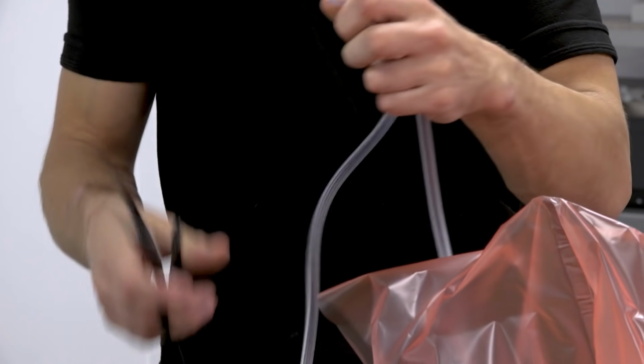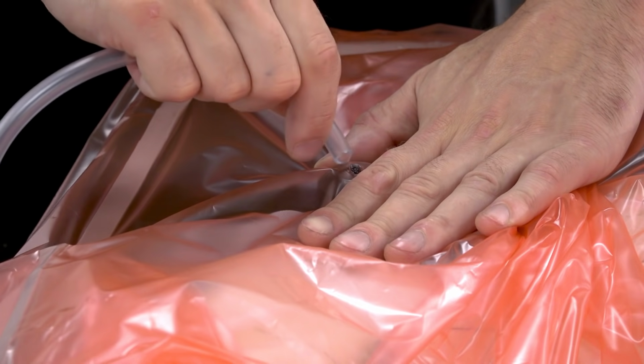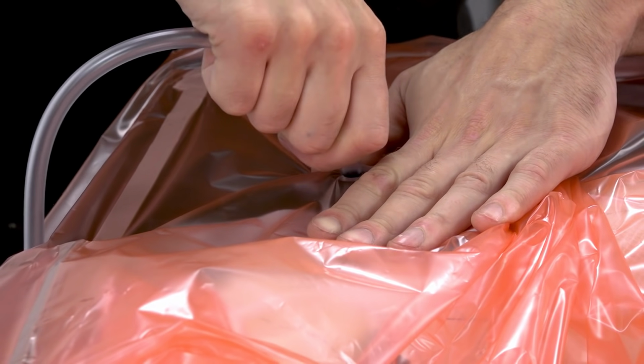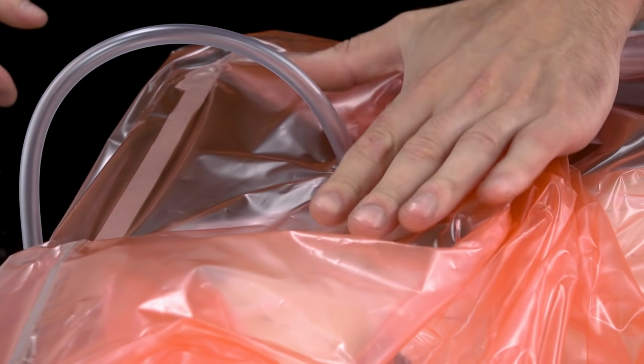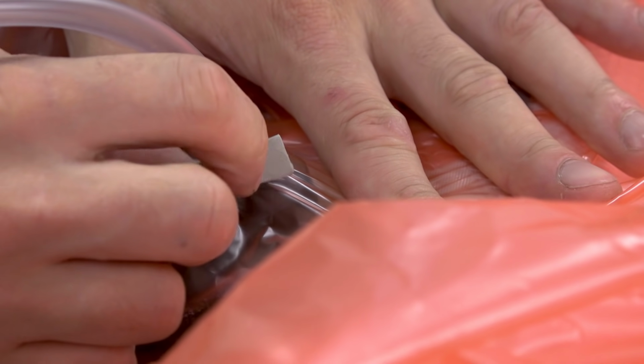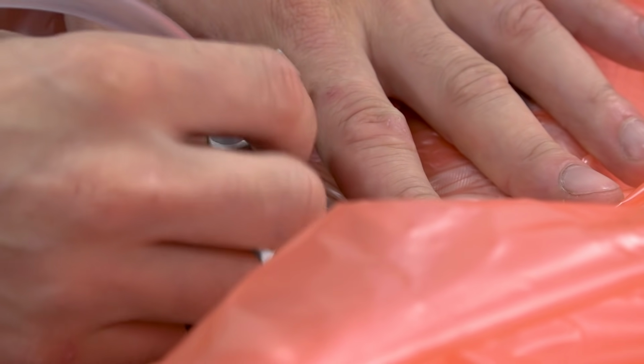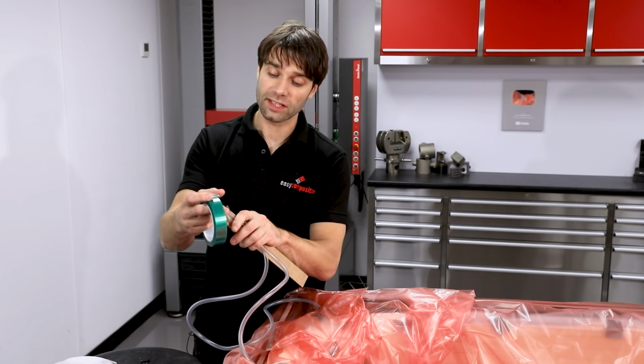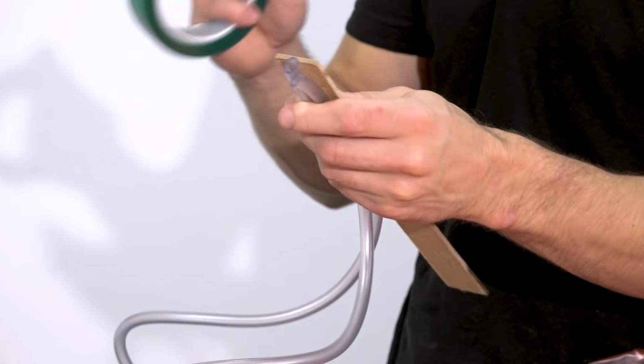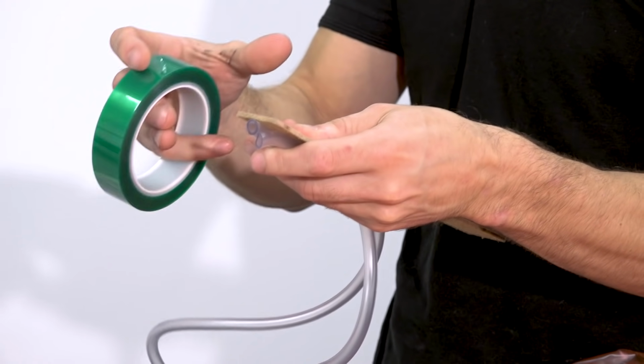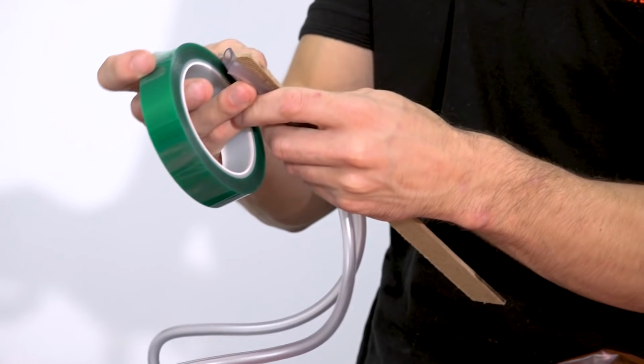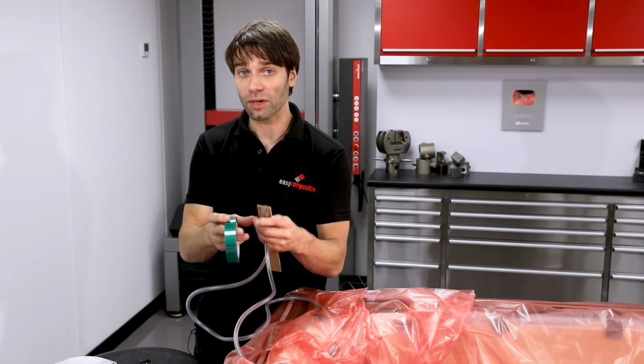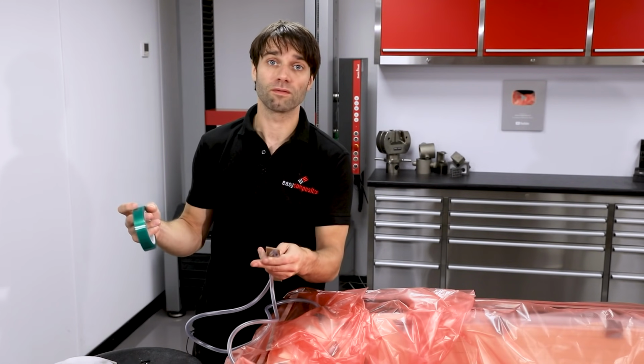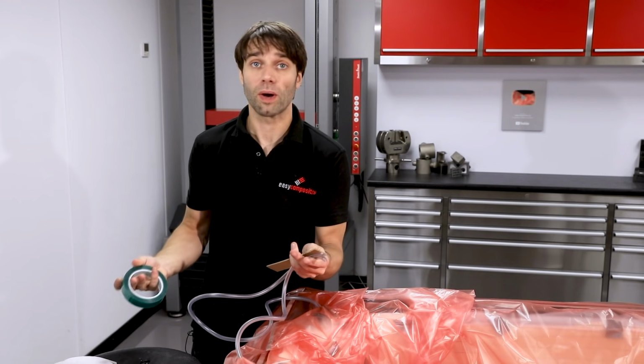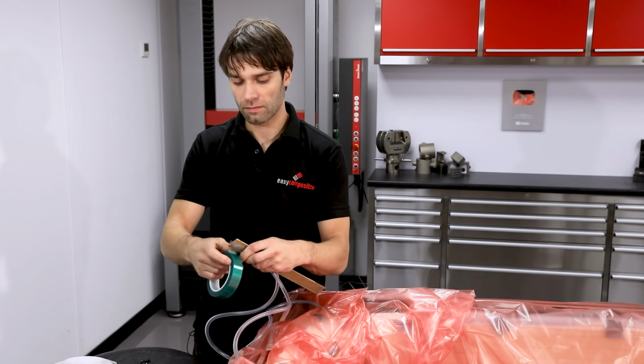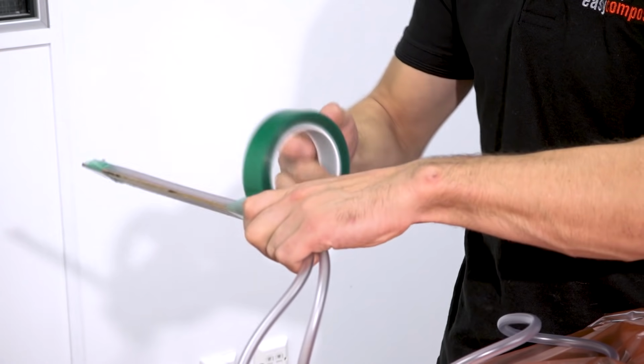The resin feed lines are connected in the same way as the vacuum line. Cutting a chamfer on the ends of the hoses helps to push them into the fittings and also prevents the tube from bottoming out and restricting the resin flow. Here I'm going to tape these hoses onto this stick, so that I can tape that into the bottom of the bucket and it will firmly hold these lines in the bottom of the bucket. It's very common, if you don't do this, for a line to fall out of the infusion and destroy what would have otherwise been an absolutely perfect part.